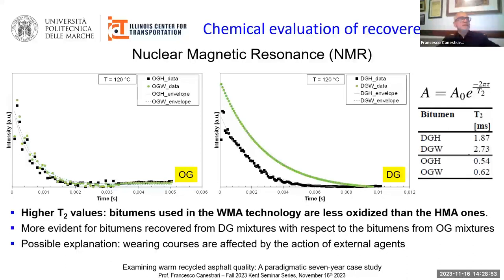Looking at the results of both open-graded and dense-graded mixtures, it's clear that the recovered binders from warm mixtures are less oxidized because their relaxation time is higher. This result is more evident for the polymer modified binders recovered from the dense-graded mixtures with respect to the bitumens from open-graded mixtures, where the difference is reduced. This is because the wearing course is affected during its service life by the action of severe external agents.